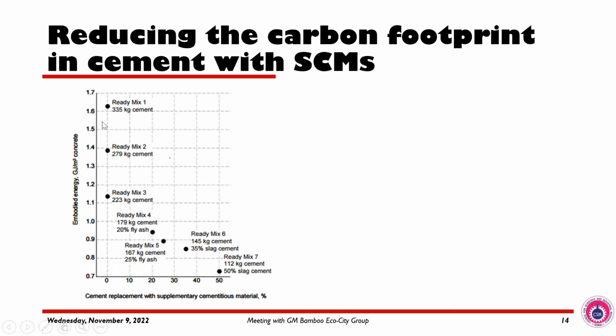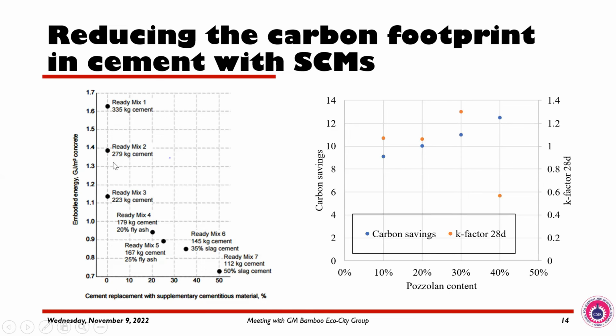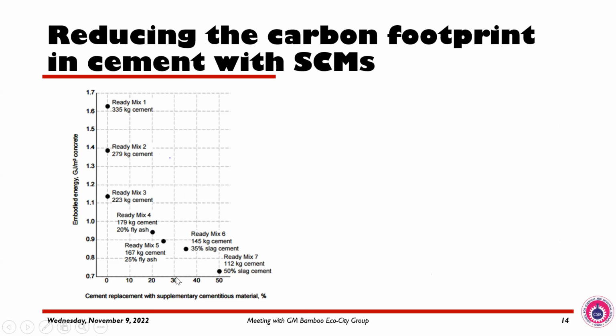So look at the graph very well. This is a ready-mix concrete containing about 335 kilograms. Now, when I say embodied energy, it is the total amount of energy that is used to produce the concrete. And the embodied energy of a material is directly proportional to the embodied carbon. The embodied carbon is the total amount of carbon that is generated by a material. So when they used about 335 kilograms of cement in a concrete mix, the embodied energy was about 1.6. But you realize that as they reduce it and replace it with supplementary cementitious materials, the embodied energy reduced, right? So for example, at 35% slag, the embodied energy was a little below 0.9 as compared to when there was nothing.